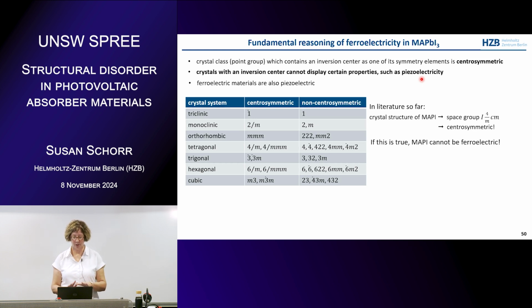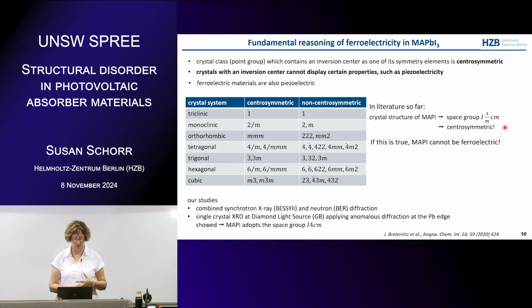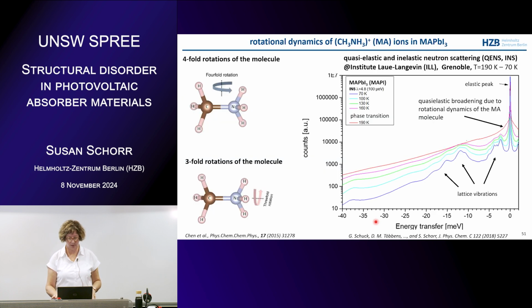So far in the literature, the space group was given as I4/mcm, which is a centrosymmetric space group. If that were true, MAPI could never be ferroelectric. So that's why we studied this not only with neutrons, as I have shown you before. We also went to the Diamond Light Source in Great Britain to do anomalous diffraction at the lead edge to really prove that MAPI adopts the I4cm space group, which is non-centrosymmetric, and then, of course, it can be ferroelectric. I think I will skip one slide, and the next one I will skip too.